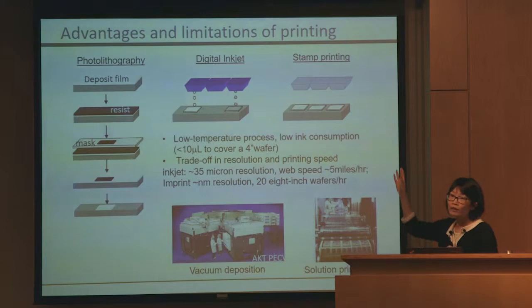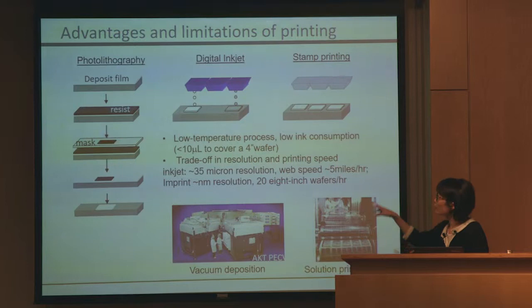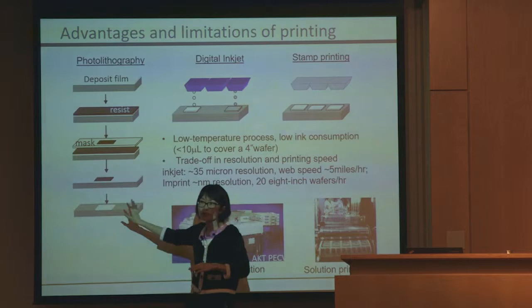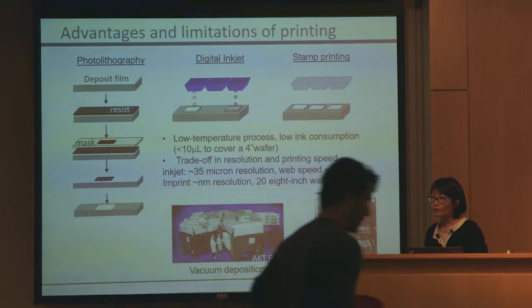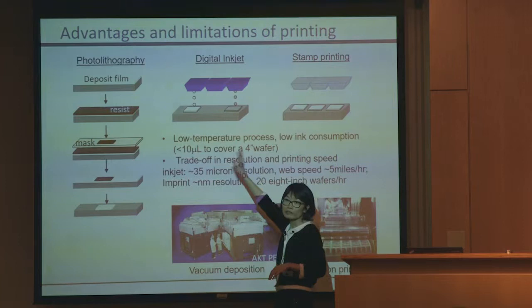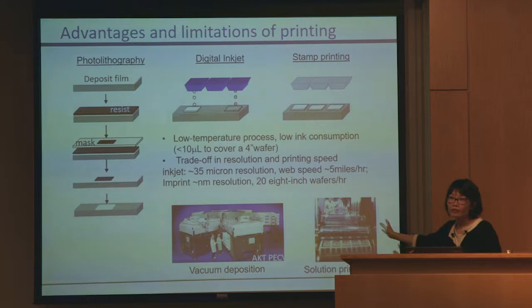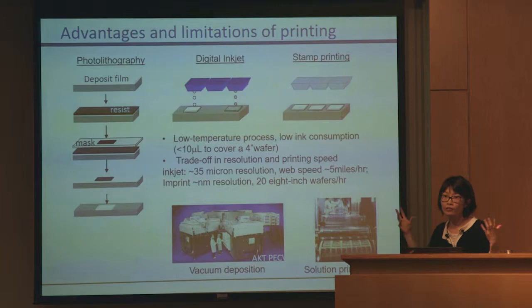In conventional lithography, you do have a subtractive step where you deposit the thin film and then you mask it and etch and pattern those deposited films. But with solution processable material, we find that you can actually use inkjet to directly deposit material on demand in the location that you want. And it actually saves a lot of steps and material. We calculated at one point 10 microliters is enough to cover a four inch wafer. That's orders of magnitude less material than a conventional process.